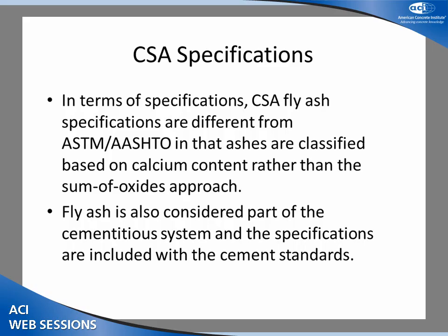In terms of Canadian specifications for ash, they're different than the ASTM/AASHTO specs, in that we classify the ashes based on the calcium content rather than the sum of the oxides, the sum of the silica, alumina, and iron approach. And I guess the sum of the oxides was meant to represent the glass phase of the fly ash. Well, I'm not sure why iron was ever in that story, because most iron in fly ash is magnetite or ferrite individual particles, so it's not part of it. And even some of the silica and the alumina is there as mullite, inert ceramic material essentially. I've never quite understood why the sum of the oxides is a smart thing to do, except it was probably easier to measure the calcium at the time using chemical techniques.